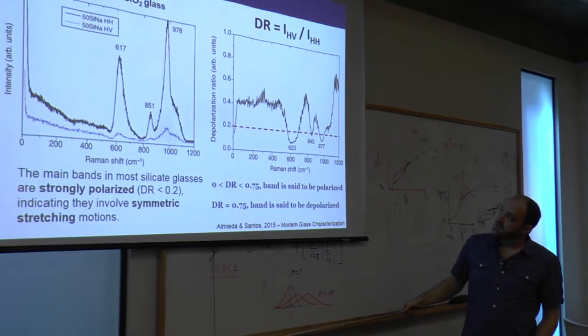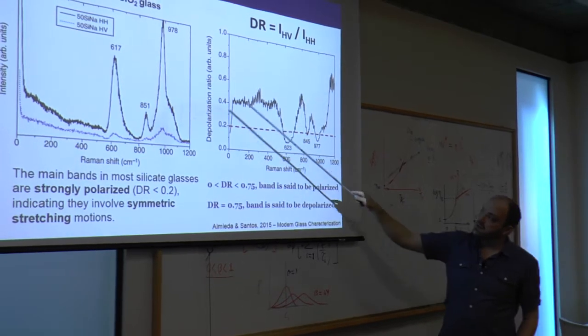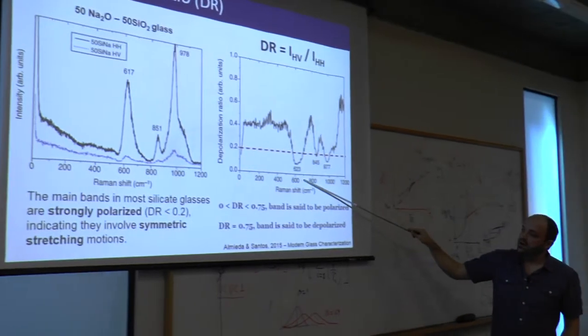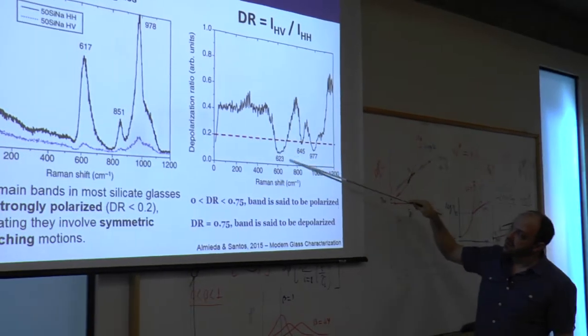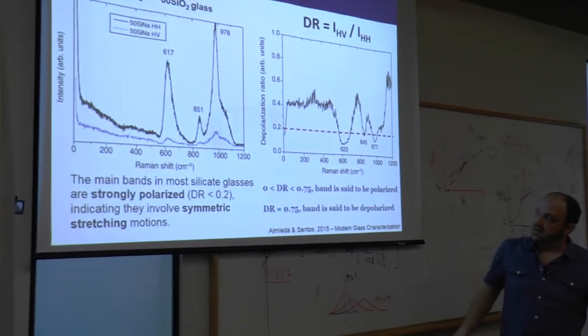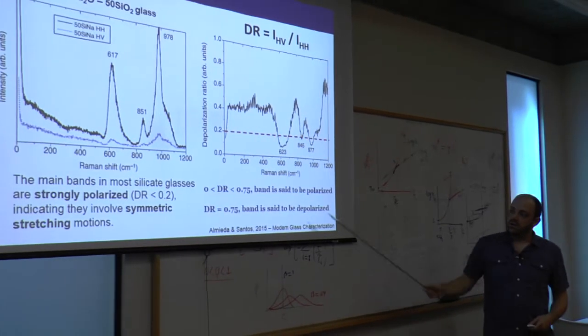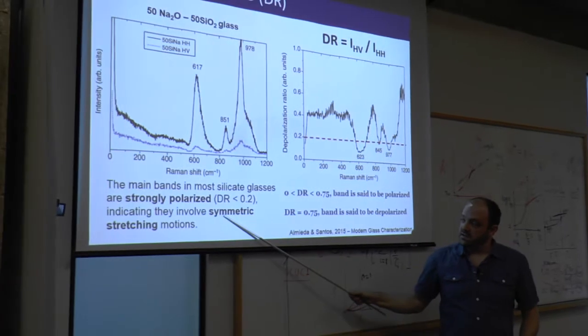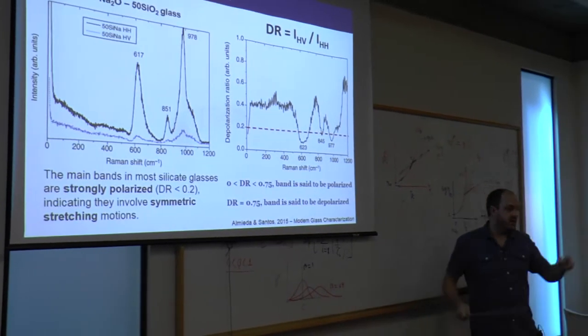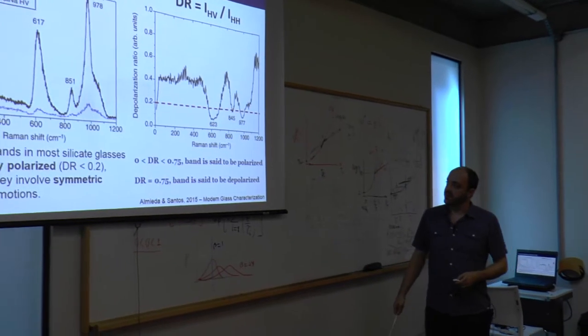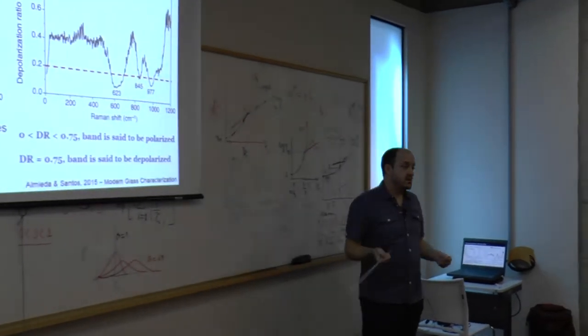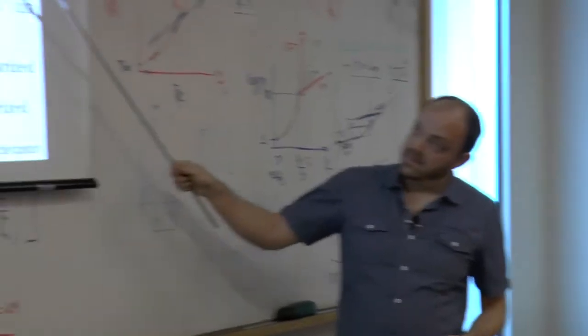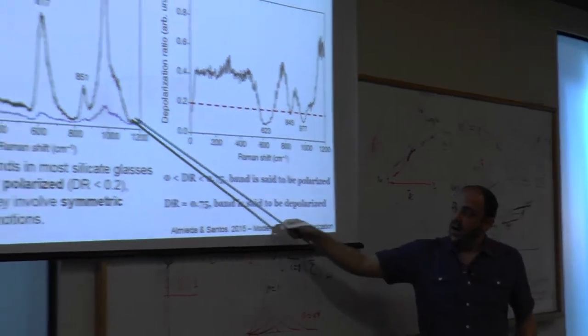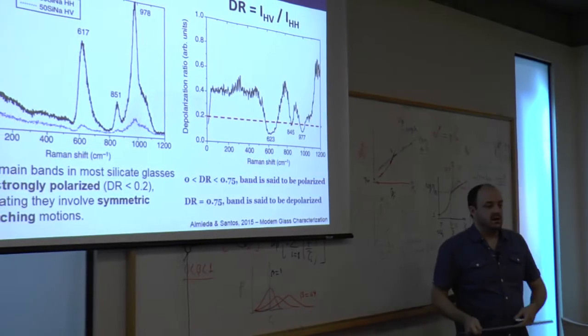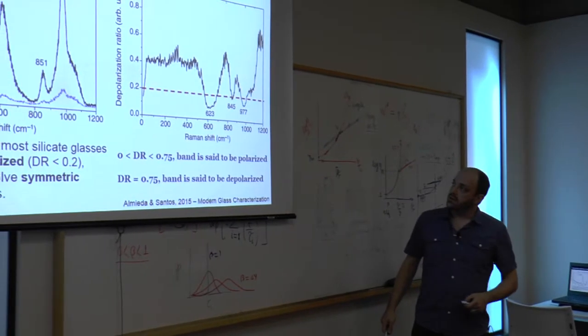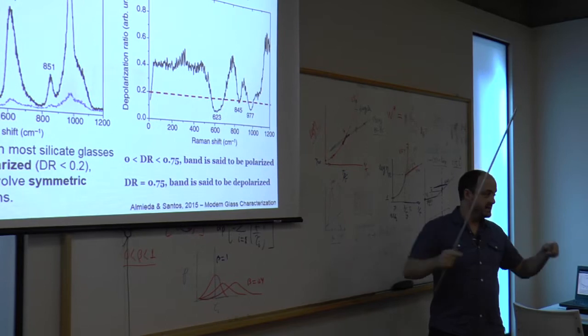And if you take the ratio of those, the depolarized over the polarized, you can see that these major features in silicates are quite polarized. They have very low depolarization ratio. So this leads Almeida and Santos to say that for silicates, most of the vibrations are strongly polarized, and the interpretation is that most of what we see is related to symmetric stretching mode vibrations and not all the wagging and the other vibrations that we showed early on. So if you have more complicated samples where there's a lot of band overlap, you can look at the depolarization ratio to get an idea of whether the band might be coming from, say, silica or titanium or something else like this. So it helps you distinguish the band positions when you have big, broad bands that have lots of overlap.